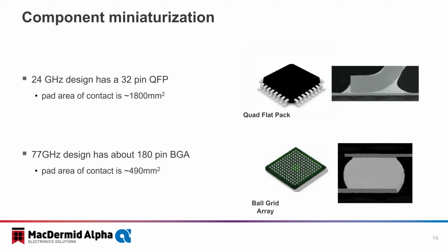In this image, on this slide, I showed you that as we advanced in our radar systems, we moved from a quad flat pack to a ball grid array. And I wanted to point out the pad area of contact. On the quad flat pack, it's about 1,800 square millimeters. But on the BGA, it goes down to 490. So you can see that the contact area is significantly smaller. A crack could be much more detrimental.